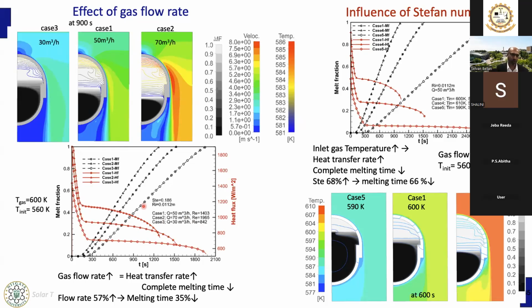The heat flux at the outer surface of the capsule has been predicted as well. As you can see, during the initial stage, the temperature difference between the outer surface of the capsule and the center of the capsule is very high, so the heat flux is very high. As soon as the melting process starts, the heat flux profile is almost flat. Like that, you can see the melting behavior accordingly, and what the heat flux at the outer surface of the capsule is. It is very obvious that when we increase the gas flow rate, the heat transfer rate increases. As a result, the complete melting time decreases. When we increase the flow rate by around 57%, the complete melting time decreased by around 35%.